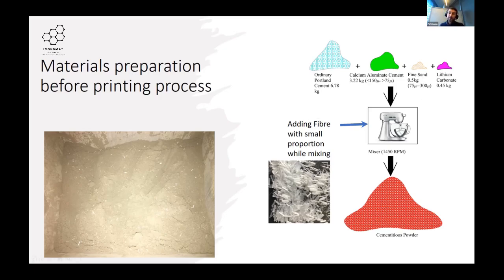Usually, if you have a cementitious material, we recommend mixing it in one mixer and rotating it for 5 minutes. During these 5 minutes, we can add the fiber in a small proportion while mixing. We have been using a 6 millimeter length of this fiber. After this, we mixed for around 10 more minutes, so it's a total of 15 minutes of mixing.